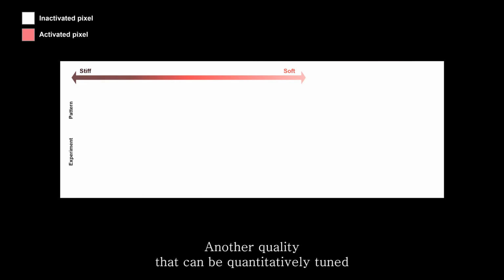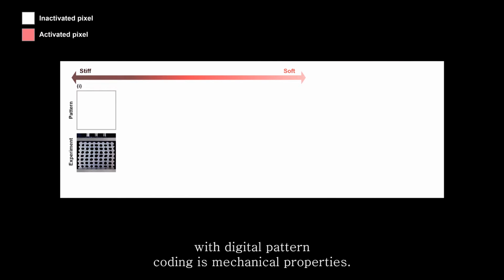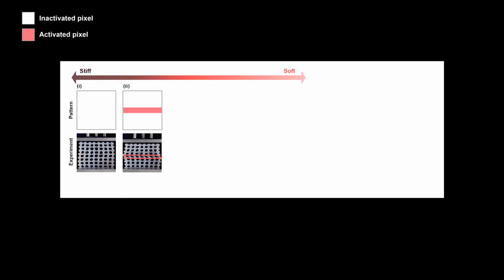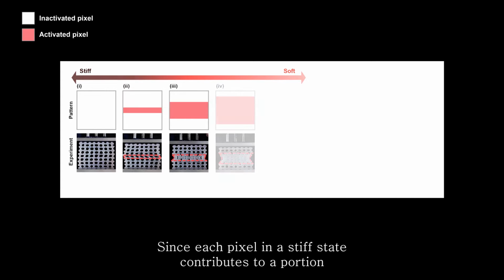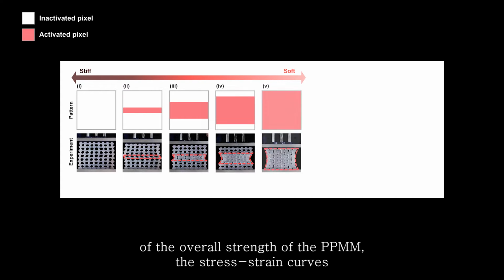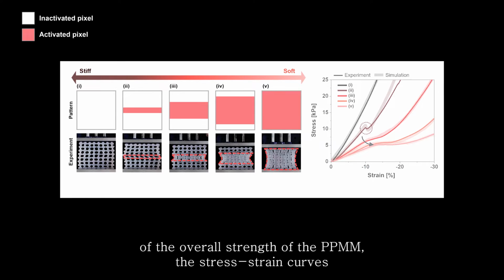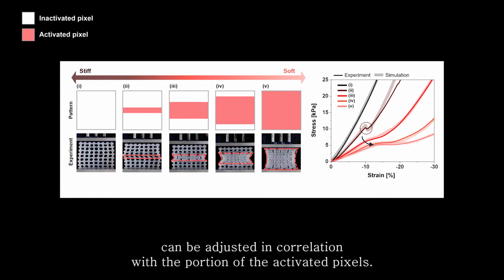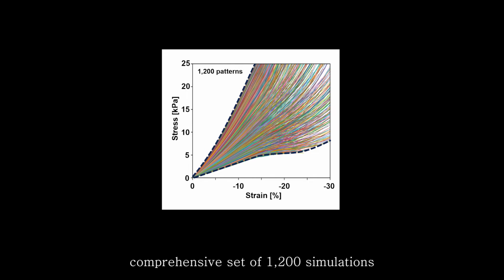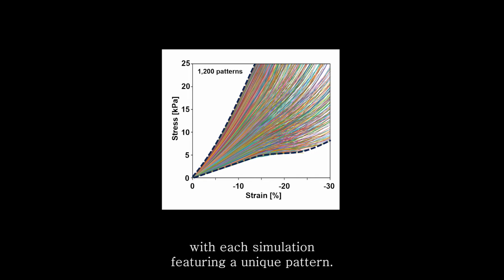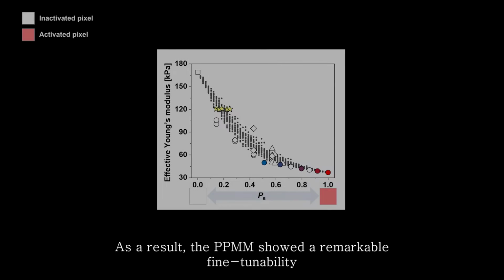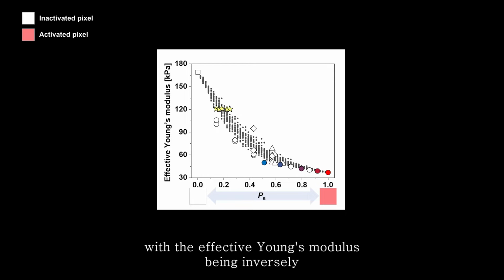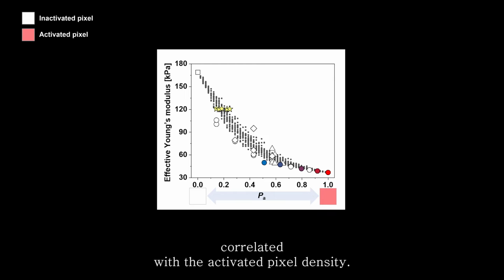Another quality that can be quantitatively tuned with digital pattern coding is mechanical properties. Since each pixel in a stiff state contributes to a portion of the overall strength of the PPMM, the stress-strain curves can be adjusted in correlation with the portion of the activated pixels. We performed a comprehensive set of 1,200 simulations, with each simulation featuring a unique pattern. As a result, the PPMM showed a remarkable fine tunability, with the effective Young's modulus being inversely correlated with the activated pixel density.